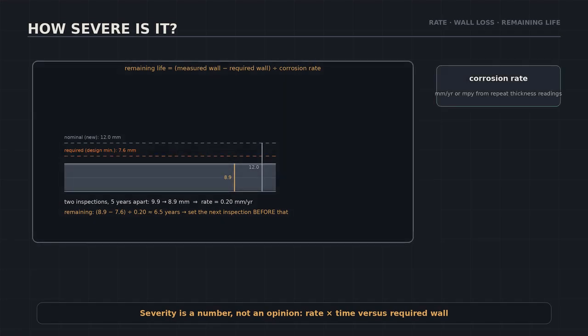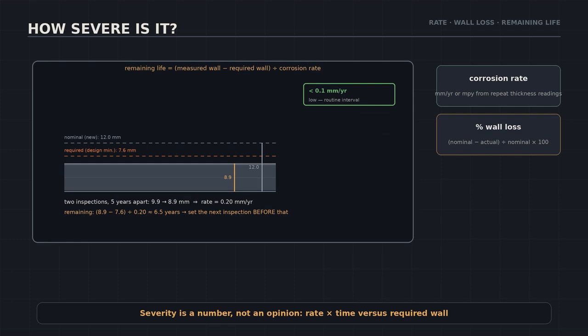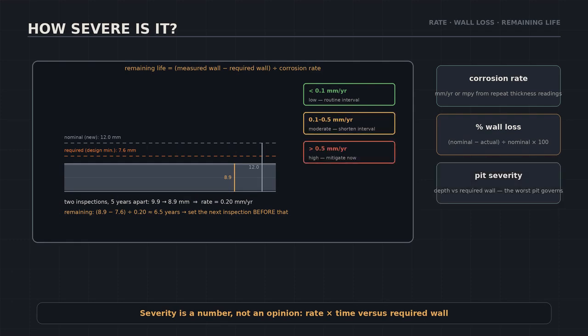Severity, then, is a number, not an opinion. Measure the wall at 2 inspections and you get the corrosion rate, here, 0.2 mm per year. Compare the measured wall with the required wall from design, and the difference, divided by the rate, is your remaining life. For pitting, the worst pit depth is what governs, compared against that same required wall. And for anything questionable, fitness for service assessment, API 579, tells you whether the remaining ligament can carry the load. Those numbers decide the next inspection date.